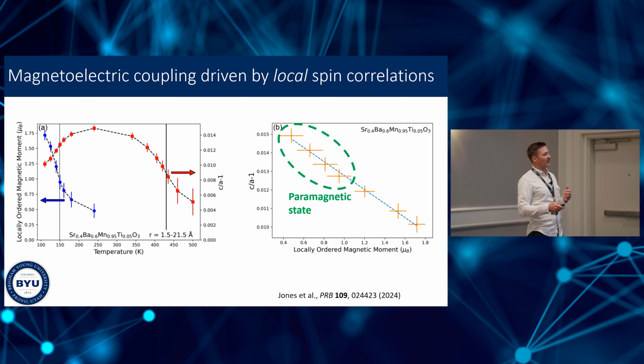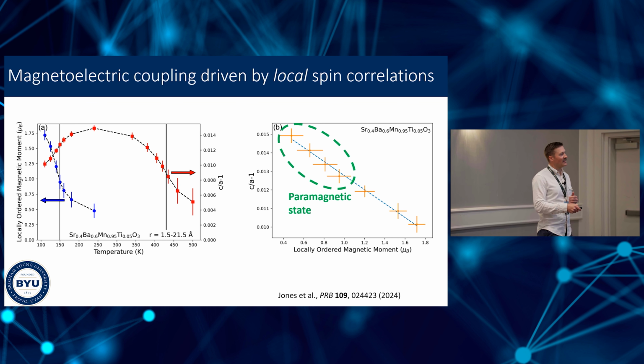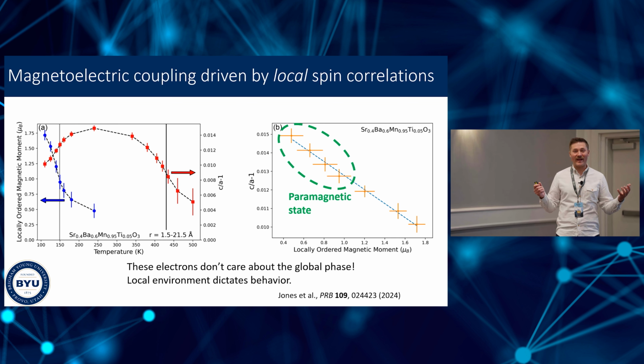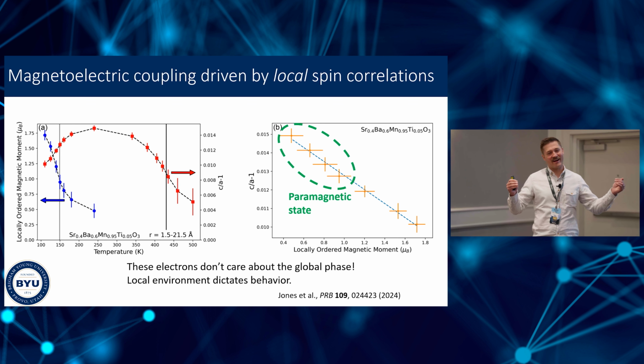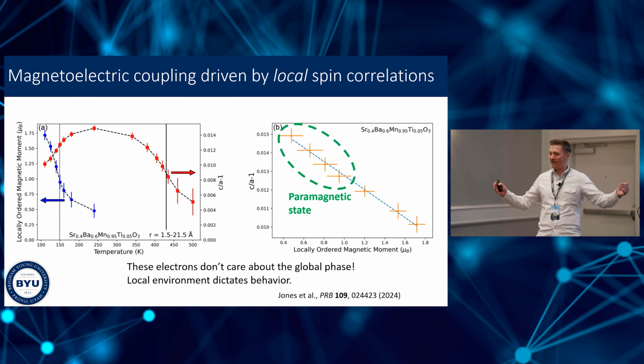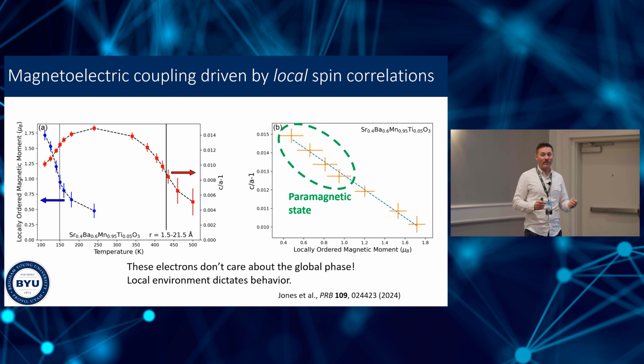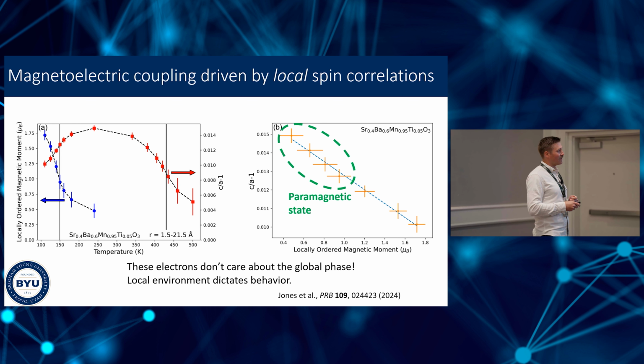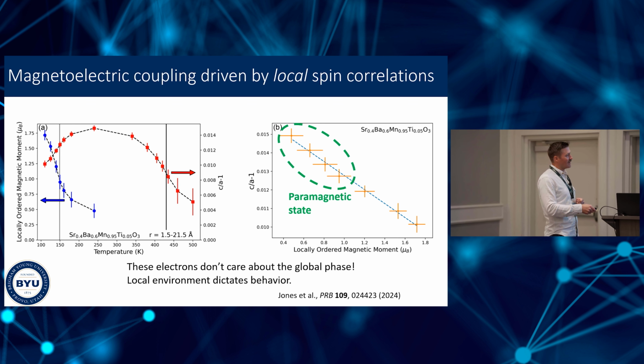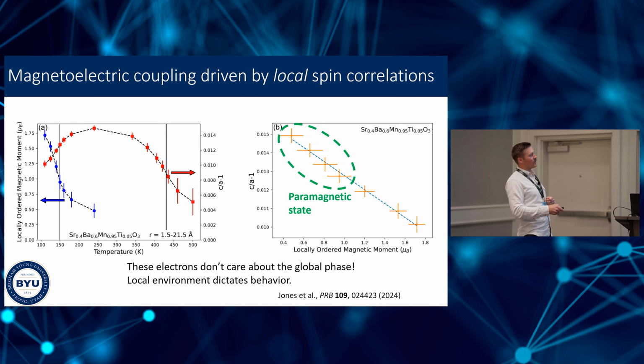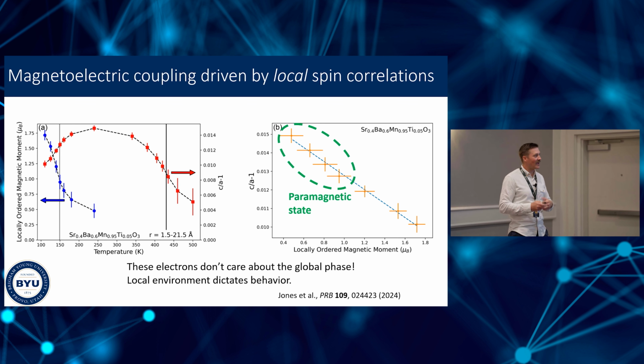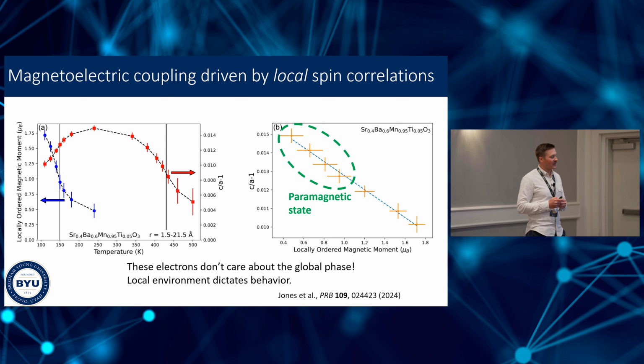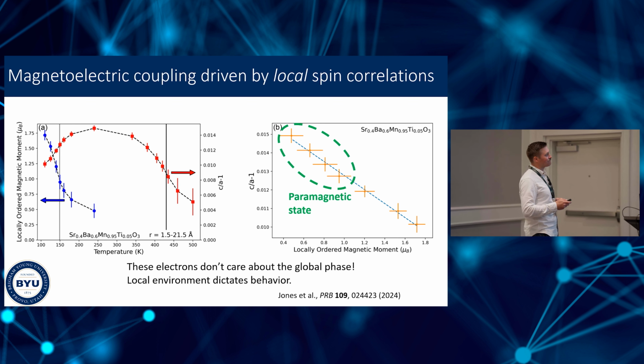So what's the conclusion from this? The conclusion is the electrons don't care about the global magnetic phase. The electrons do not care if you have long-range antiferromagnetic correlations or not. They are responding to their local environment, the short-range magnetic correlations that are present. The local environment dictates the multiferroic behavior in this compound. Okay, very similar to what we saw for manganese telluride.